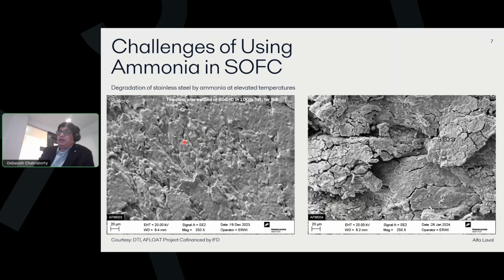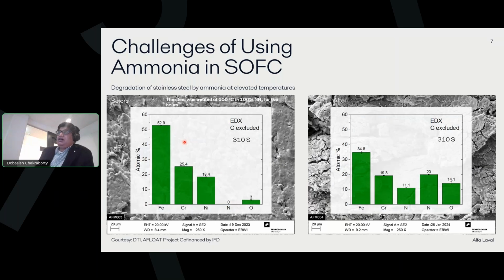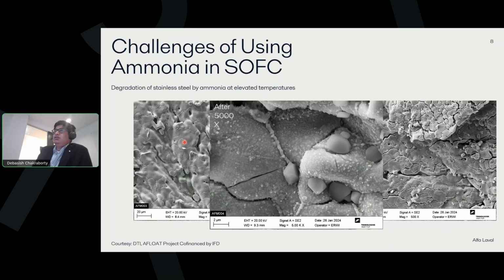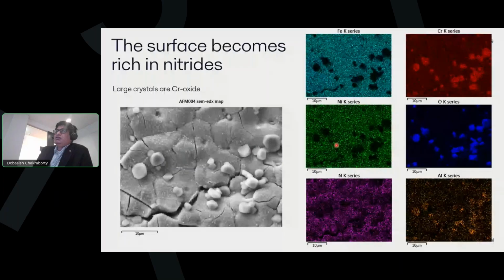Before and after. And if you see what is in there after exposing to ammonia, this is 100% ammonia, just so that you remember, you see a lot of nitride. There is also oxide, which was a surprise to us, but a lot of nitride is formed. In the close up you see big crystals on the surface, which are chromium oxides, but you also see a huge amount of nitrogen on the surface. So the protective chromium oxide layer is totally disintegrated when exposed to ammonia at these temperatures.